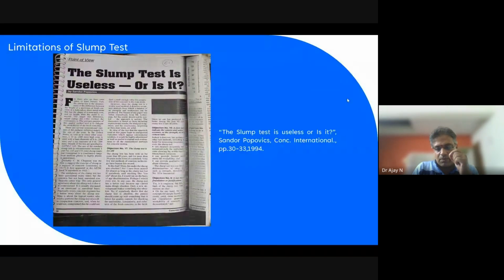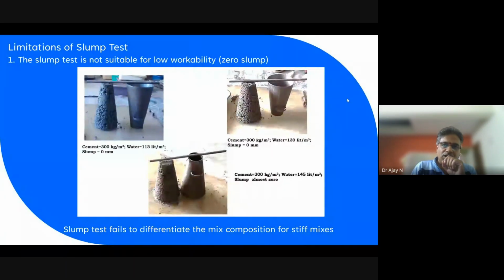Based on this paper, we conducted some experiments in our laboratory, especially at BMS College of Engineering during my research work. The first question: the slump test is not suitable for low workability mixes, because IS 456 clearly says 0 to 25 mm for road application. So based on this, we started with low workability mixes with a very conventional method, using only 4 ingredients. We are not introducing any additional admixtures. Here cement is 300, water is 115. The slump shows 0, because it is a very harsh mix.